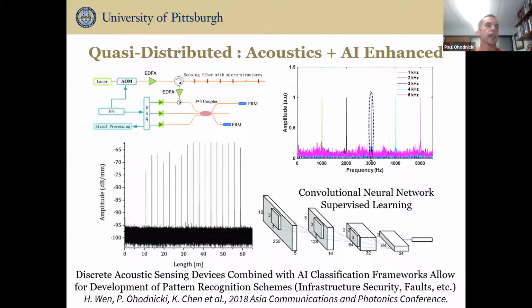The other thing that you can do, again work by Kevin Chen's group, is you can look at things like quasi-distributed measurements of acoustics, and then also look at taking the large amounts of data. So with acoustics, you don't just get a point measurement, you get a frequency spectrum. So it's a tremendous amount of data, because for every point, you may have thousands of data points associated with the frequency spectrum. So you end up with very large data sets.